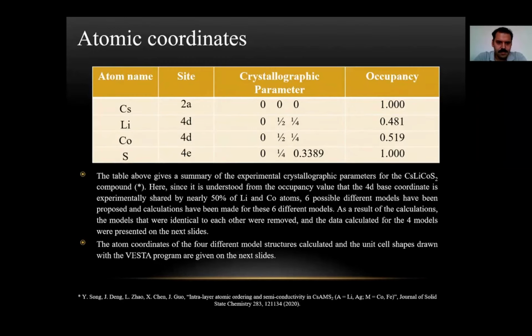Here, since it is understood from the occupancy value that the 4d base coordinate is experimentally shared by nearly 50% of lithium and cobalt atoms, 6 possible different models have been proposed and calculations have been made for these 6 different models. As a result of the calculations, the models that were identical to each other were removed, and the data calculated for the 4 models were presented on the next slides. The atom coordinates of the 4 different model structures calculated and the unit cell shapes drawn with the VESTA program are given on the next slides.